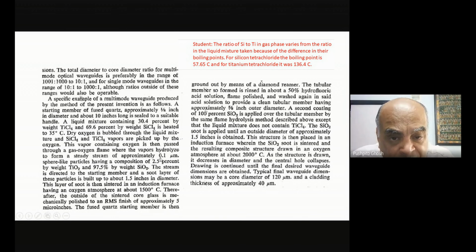A stream of approximately 0.1 micron sphere-like particles having a composition of 2.5% by weight TiO2 and 97.5% by weight SiO2. The stream is directed to the starting member. Okay, so you're forming effectively like a soot. That's what you're forming. It's just like we have kajal, in a very colloidal form. Okay, so they were putting that on the outer rod, this particular rod.